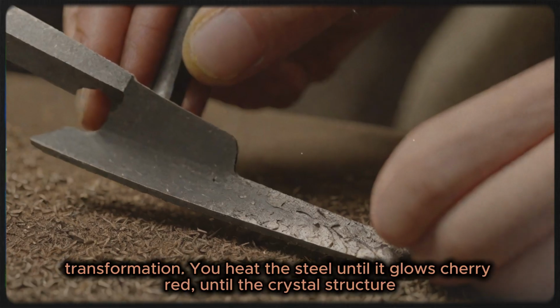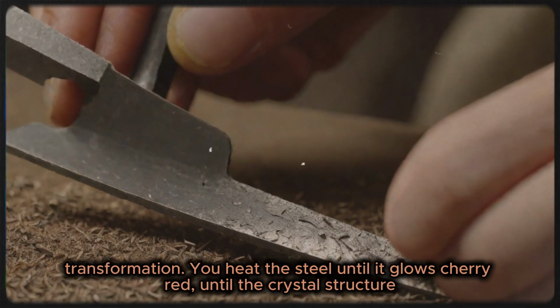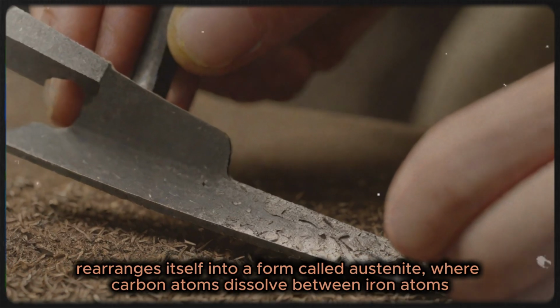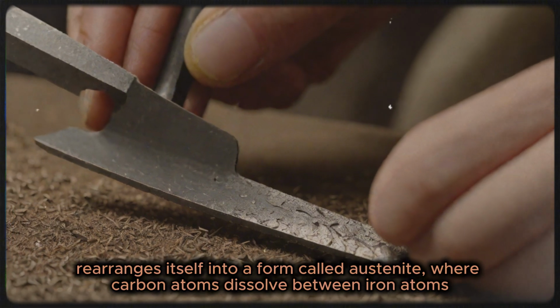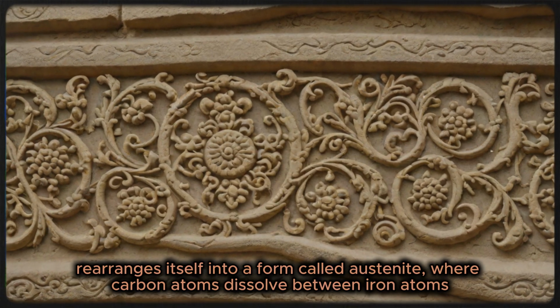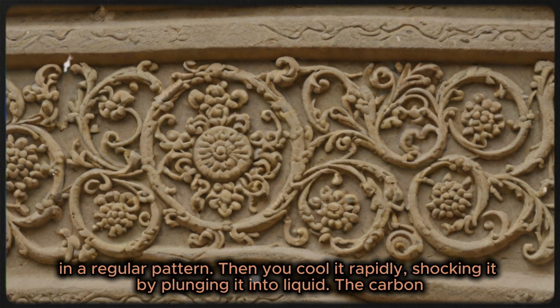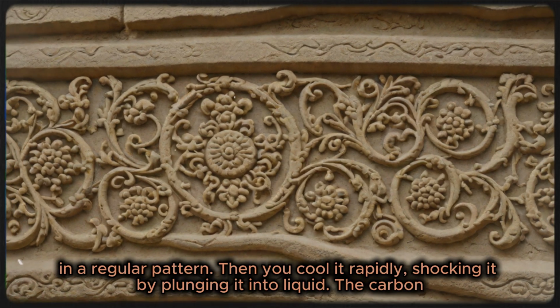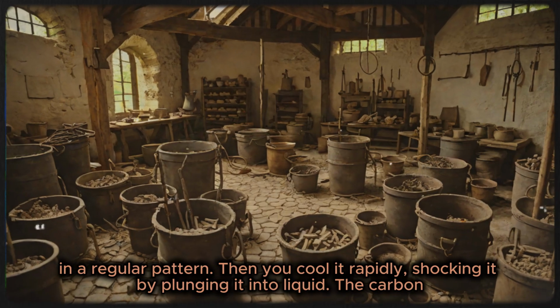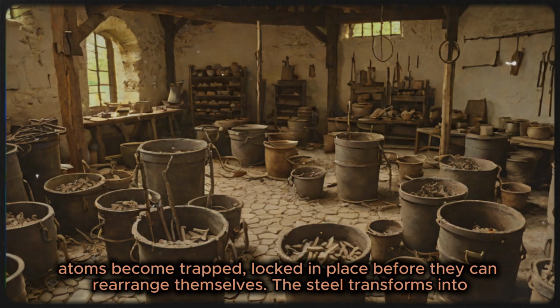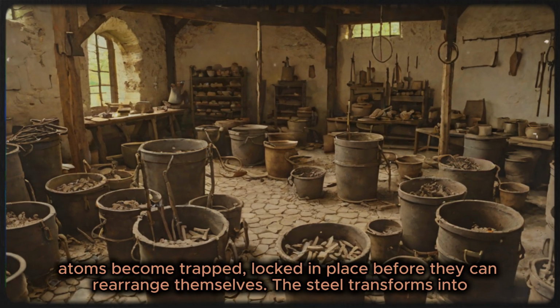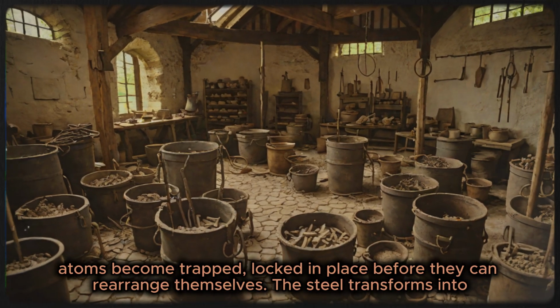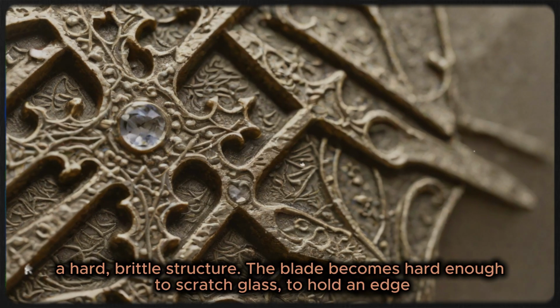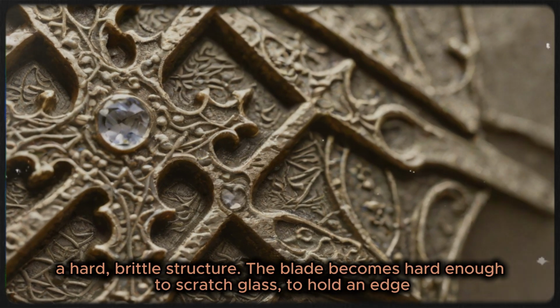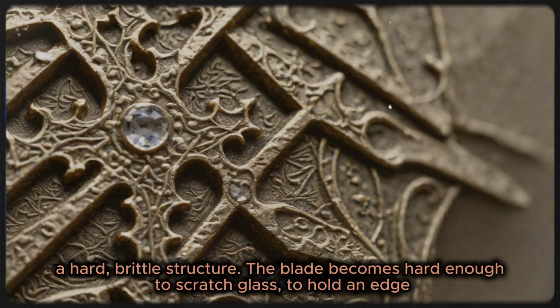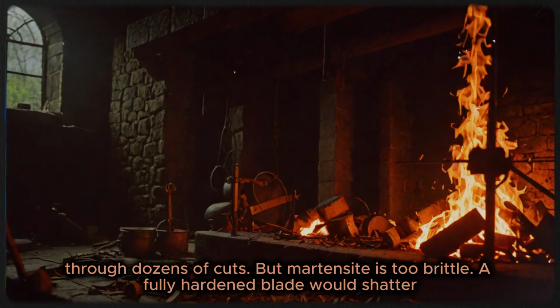Hardening is transformation. You heat the steel until it glows cherry red, until the crystal structure rearranges itself into a form called austenite, where carbon atoms dissolve between iron atoms in a regular pattern. Then you cool it rapidly, shocking it by plunging it into liquid. The carbon atoms become trapped, locked in place before they can rearrange themselves. The steel transforms into martensite, a hard, brittle structure. The blade becomes hard enough to scratch glass, to hold an edge through dozens of cuts.